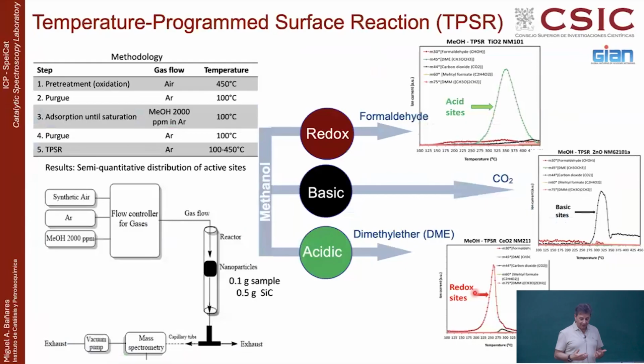But because you not only measure the number of sites, but also the reactivity, you can tell more. In the most simple cases, on a redox site, this methoxy group will be oxidized to formaldehyde. By detecting online on the mass spectrometer, you will see that. If it is on an acidic site, two nearby methoxy groups will dehydrate into dimethyl ether and water. So you will get dimethyl ether as a reporter of acidic sites at the surface of your material. And also, if there are basic sites, they will adsorb the methoxy group so strongly that by the time it comes out, it's already burned to carbon dioxide. And you can have combinations and bifunctional sites, basic and redox, basic and acid, and get dimethoxymethane, methyl formate, but this is more complex. In any case, these are the key basic compositions.